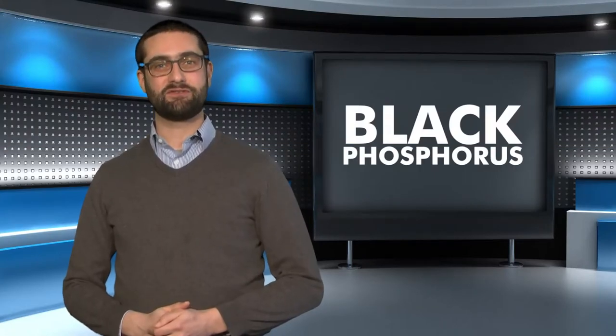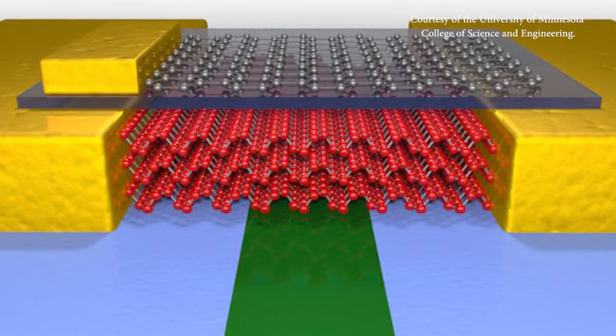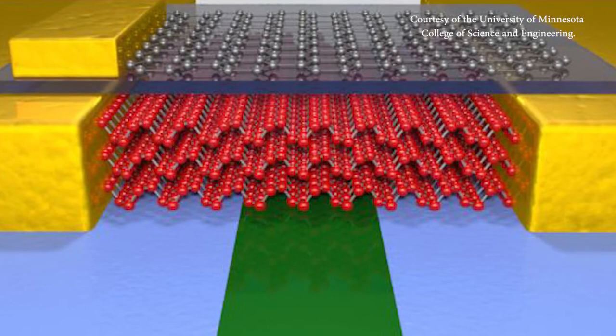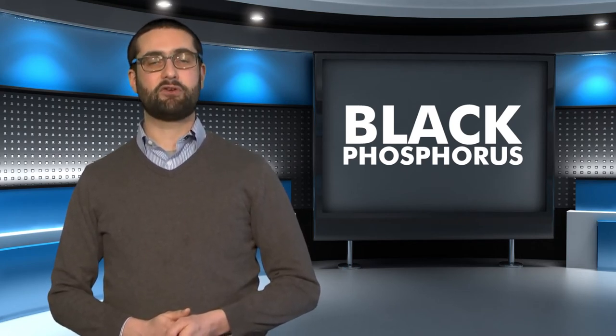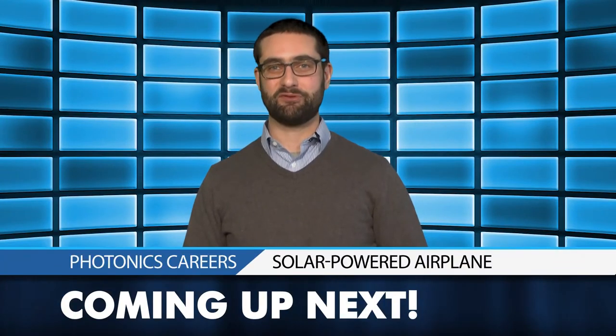Thanks, Rod. Next, we go to the University of Minnesota, where researchers are experimenting with a new 2D material that could work better for optical communications than graphene or even germanium. Black phosphorus has been known for more than a century, but its potential as a semiconductor with a tunable band gap only came to light within the past year. According to the Minnesota team, the light-detecting and emitting properties of black phosphorus make it a good candidate for use in optoelectronics. The researchers used black phosphorus to build optical circuits capable of transmitting data at up to 3 gigabits per second using the near-infrared telecommunications band. They said it operated well under bias and with very low dark current. The research was published in Nature Photonics.